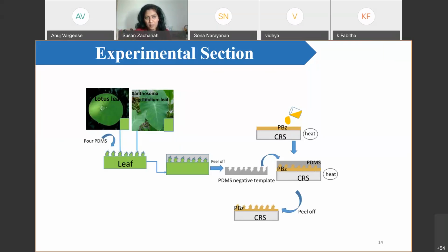Before keeping the PDMS negative template, I have given different times to make it a little bit cured, a little bit hard, and then placed the PDMS negative template over it, pressed and heated. After curing the PBz, I peeled out the PDMS, so that I found the PDMS got the similar pattern of the leaf which I have used. This is the flowchart of the experiment which I have done.